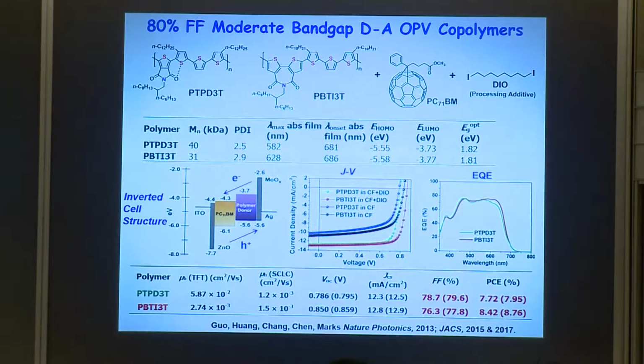But if you really know for these organic molecules how to control the HOMO-LUMO spacing, which is the band gap, a materials person would say the band gap, and the mobility, and you do little tricks like this. These weak non-bonded interactions help planarize the structure. Think of these as tapes then. We'll dope them with a fullerene or some other acceptor, and you can make solar cells. And so here's the front transparent window and the other electrode, and so holes are going to go this way, electrons this way when you turn on the light. The first thing that struck us when we made these and looked at the initial data was this kind of squareness looks like silicon or SiGe. Most organics are much less abrupt here, and it has to do with your ability to extract current at this voltage, and it's called the fill factor.